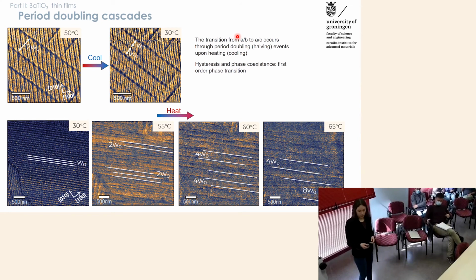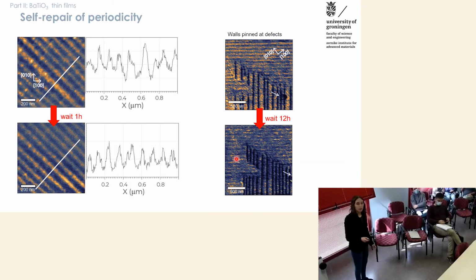And we also see a certain hysteresis in this transition. So it means that upon heating and upon cooling, the temperatures are not exactly the same. So this is a classic example of a first order phase transition, where we have a coexistence of the two phases over a broader temperature range, so not a critical transition. And what we also see is that upon giving the system some time to relax at each temperature, wherever we have some defects and some wrong periodicity due to domain pinning by defects, we see that a relaxation occurs, and then the equilibrium periodicity is achieved after some time. Only in the case the defects are not too big. So when we have something like a huge particle, the domain just gets pinned there, and the periodicity is not recovered.